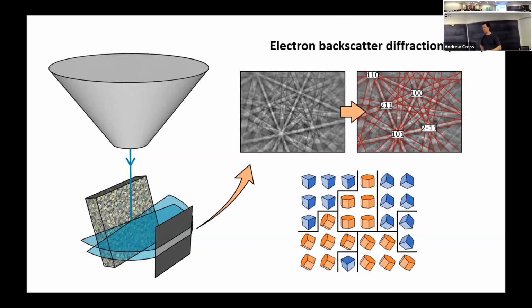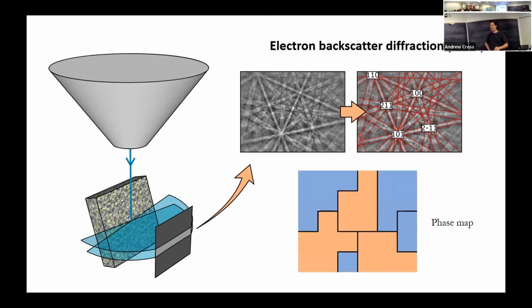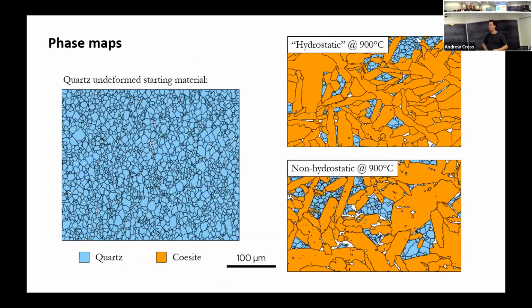So we can take this information and divide it up into regions of different phases, orange versus blue, and different orientations, and build up phase maps and also orientation maps, where the colors here correspond to different crystal orientations. So these are phase maps. On the left, we've got our quartz starting material. We took our quartz material up to pressure and temperature conditions and then brought it back down, just to see what it looks like right at the start of our experiment. We've got grain size on the order of a few microns, on up to 10 microns, let's say.